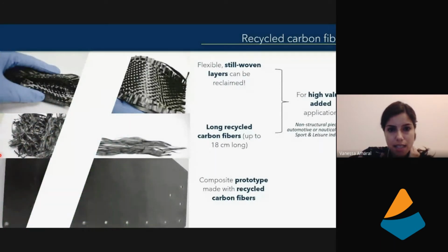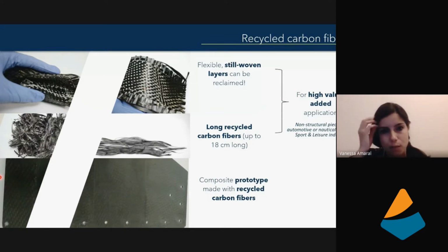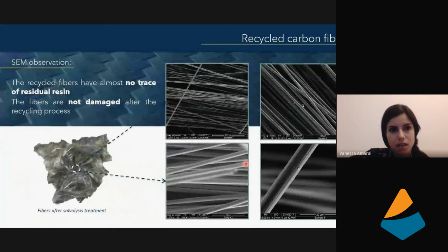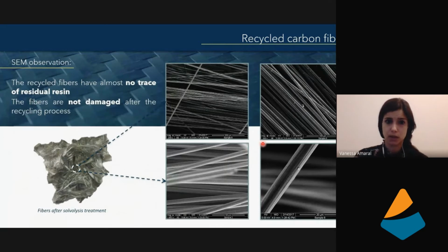So to continue, as the process itself is quite gentle, if the material is still woven, we can recover the still woven material after the recycling, which can be interesting, especially for applications in the sport and leisure industries. Or we can recover long fibers that can then be processed into yarns for higher value applications. So here are some characterizations. Here are images taken using a scanning electron microscope, where we can see that we have almost no trace of residual resin within the fibers, and we can see that there is no damage in the fiber itself.